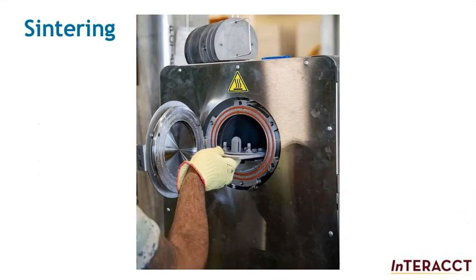The last step in actually creating the finished parts is to sinter the green parts until the powder is completely fused. Sometimes this is followed by infiltrating the space left by the evaporated binder with the secondary metal. By nature of the task, the sintering step involves little to no potential for exposure as long as the furnace is properly exhausted. In order to reach the required temperatures and atmospheric conditions, the sintering chamber must be entirely enclosed and tightly sealed. There may be a slight potential for dermal exposure when placing green parts into the furnace, but once sintering and infiltrating are complete, the object is an article, with no further potential for chemical exposure unless post-process sanding or grinding is required.